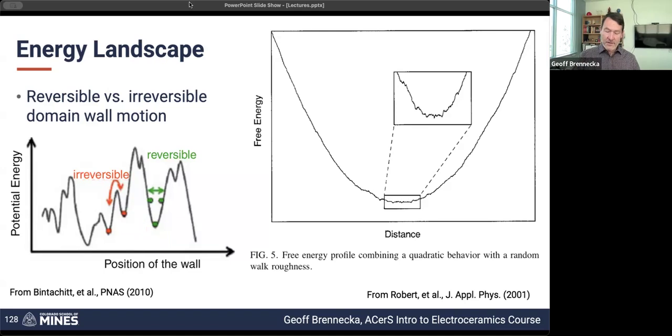If, on the other hand, where you are within this noisy energy landscape is such that you apply a field in one direction and it actually does hop over a barrier and land in a different well, then that's irreversible, because now to push the atom back into its original well, you have to go over a higher barrier, because this distance is higher than that distance.